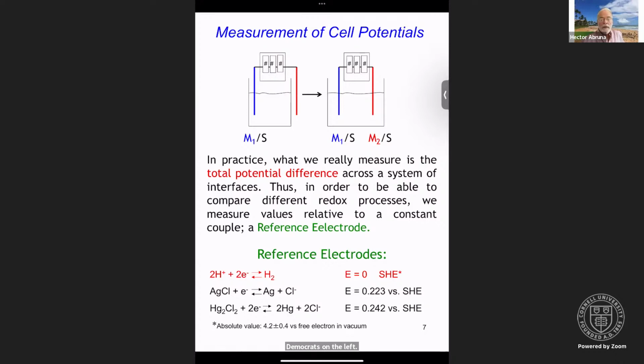And so what this tells us is that rather than measuring a single electrode, in practice, what you do is measure the total potential difference. So here, emphasis on the total potential difference across a system of interfaces. In this case, the interfaces would be metal 1 to solution, solution to metal 2, and then across the terminals of the meter here. And so this brings up the issue. So how do we establish at least some way to rationalize potentials? In order to be able to compare different redox processes, we measure the values relative to a constant couple or redox couple, and this is what we call a reference electrode.